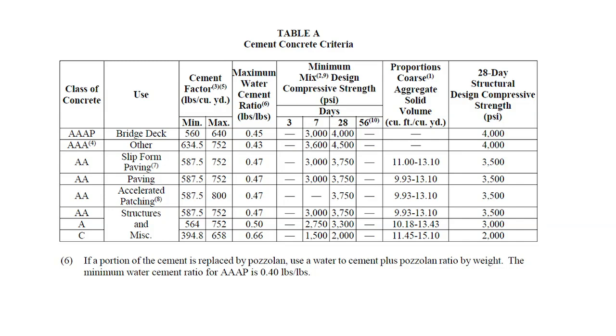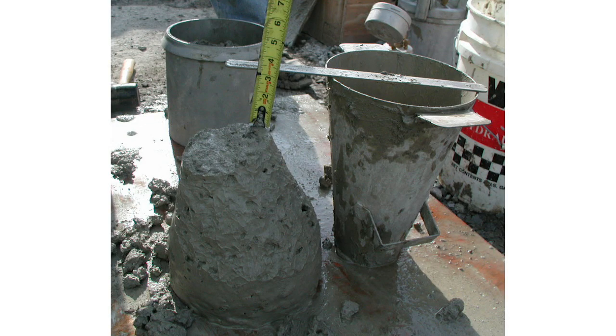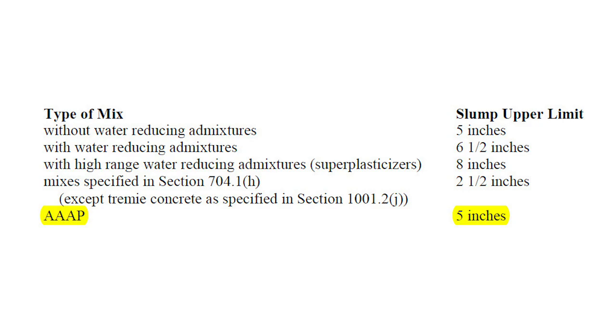The concrete type to be used for all bridge decks is Class AAAP. AAAP bridge deck concrete requires a 7-day minimum compressive strength of 3,000 psi and a minimum 28-day compressive strength of 4,000 psi. AAAP requires a minimum water-to-cement ratio of 0.40 pounds per pound and a maximum water-to-cement ratio of 0.45 pounds per pound. AAAP has a maximum upper slump limit of 5 inches.